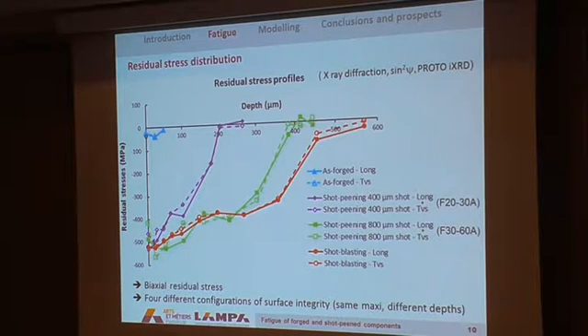And we also performed some measure of residual stress. And you see here the 4 conditions, and you observe some biaxial residual stress everywhere in depth. And we tried to get approximately the same maximum value of residual stress, around -500, but by changing the condition of the shot peening to get different depths of the profile.